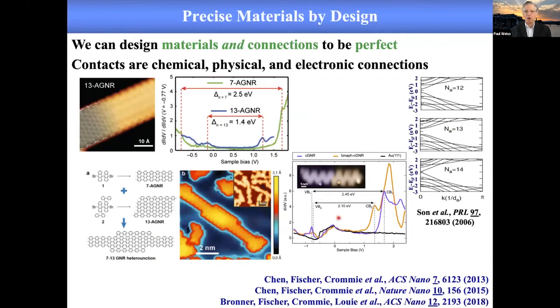I had thought, well, you can't make a device that's only linear because it just keeps going. But what they did in these nice demonstrations was show, for instance, for the armchair nanoribbons, by varying the width, you build a device in line by having the different band gaps in the center and on the outsides. And then they also did the side group functionalization, where using these zigzags and different functionalization on the sides, they were able to get different electronic properties across these segments. So I was very excited about that.